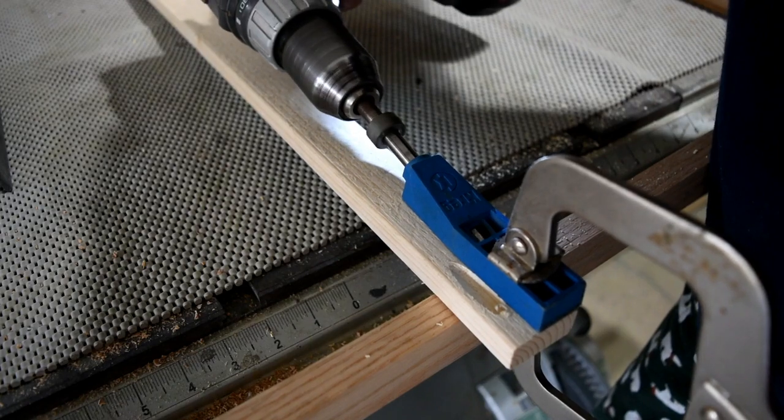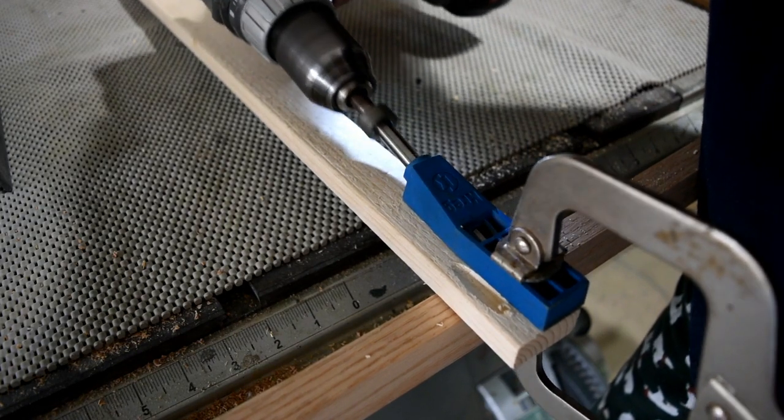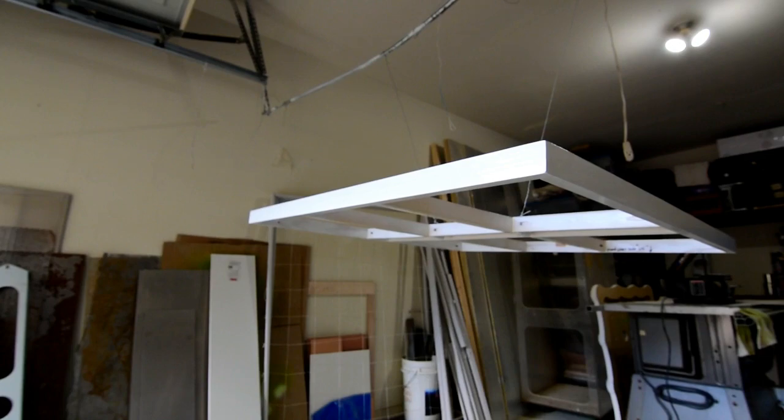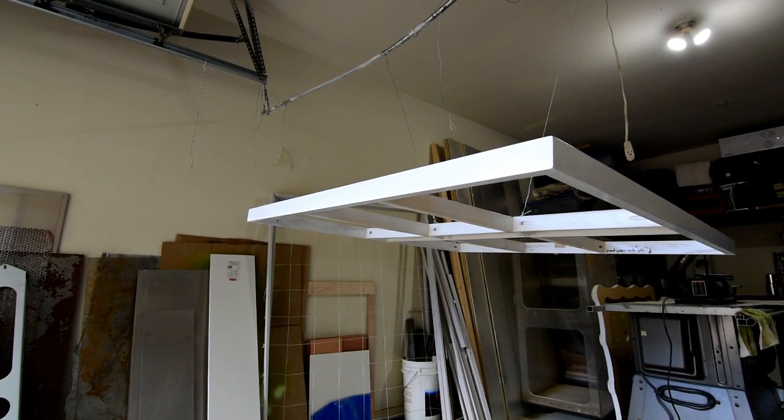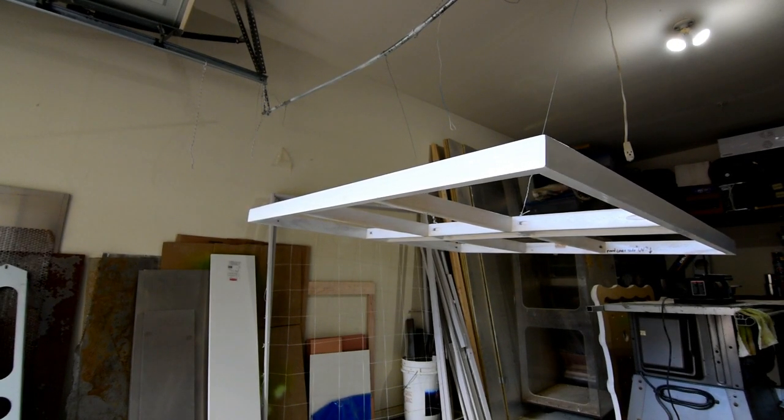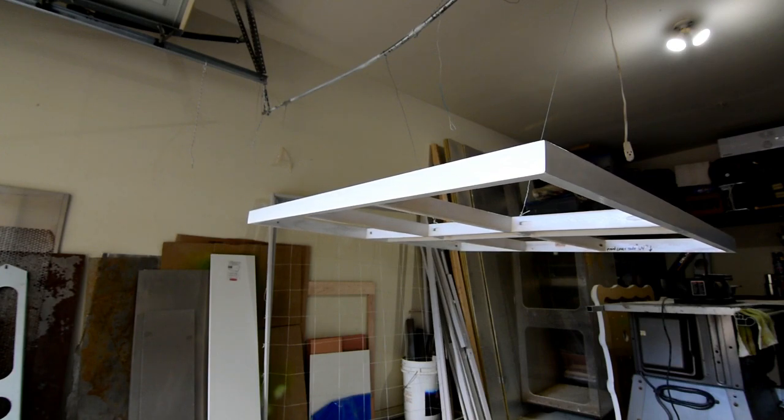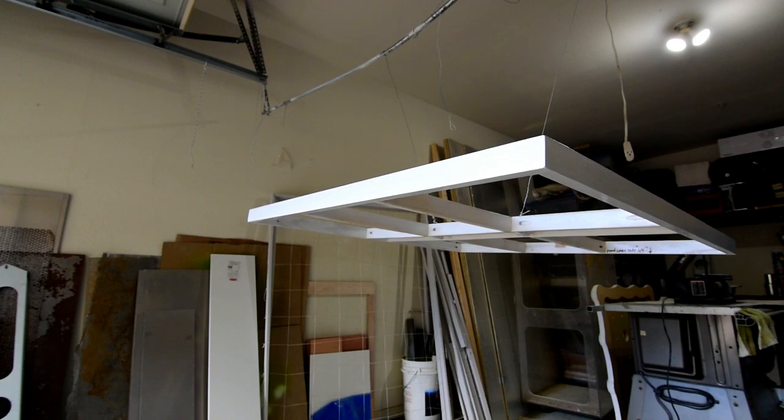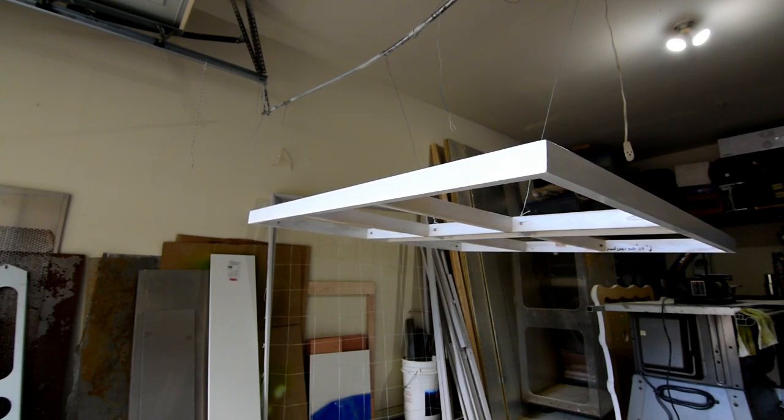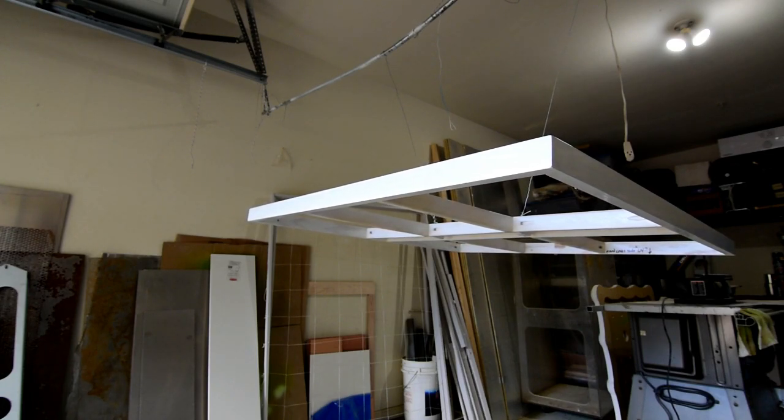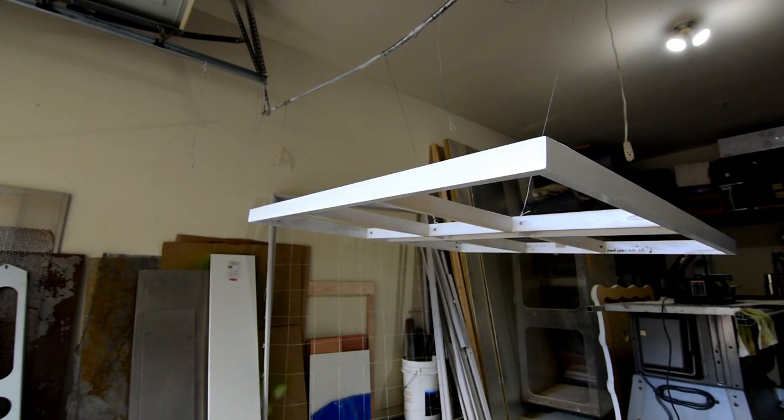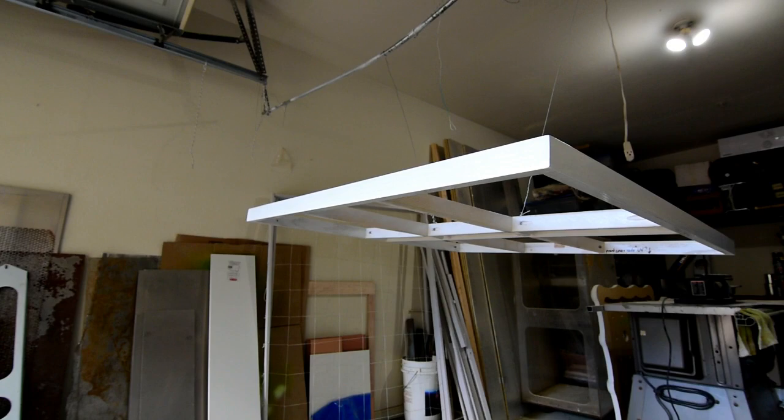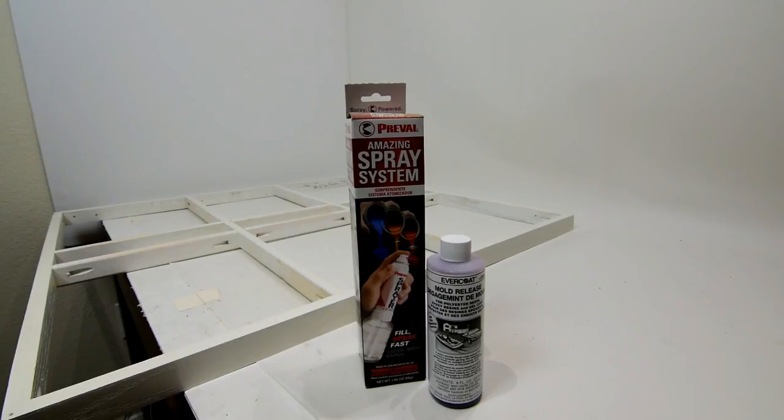And this wood will be basically painted and sealed so that the carbon fiber doesn't stick to the rim. So I got the frame perfectly square and then went ahead and painted it. I just used regular white high gloss spray paint from Lowe's, just painted with a couple nice coats, then wet dried down the bumpy spots and then hit it again for a nice like silky smooth type of finish. The next step is just to wax it down with some mold release wax and then spray it with something special called PVA.